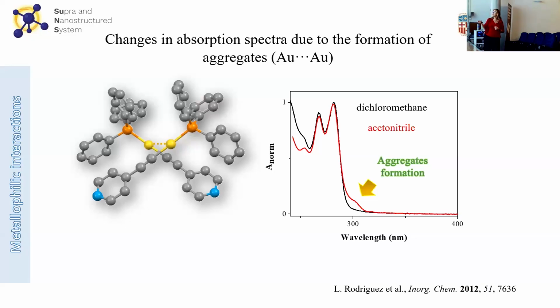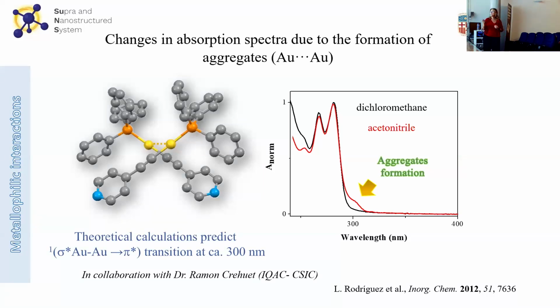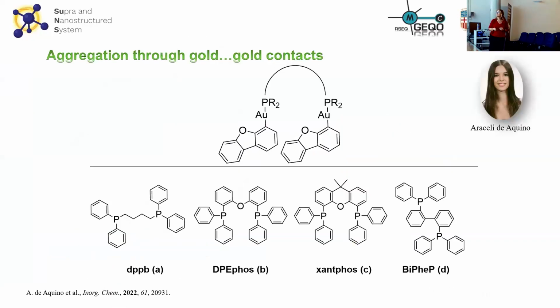And we can predict that whenever we find this broad band, weak in intensity but broad above 300 nanometers, it is directly correlated with the presence of aurophilic contacts. And in collaboration with Ramon Crehuet, who made some calculations, we can ascribe this band to this transition, supporting the presence of these aurophilic contacts.